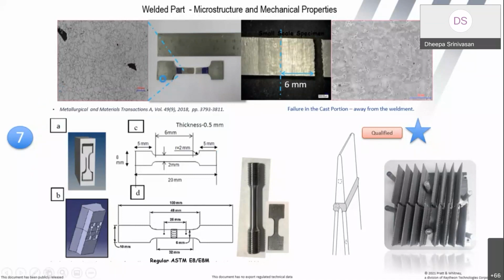But the other challenge I'm highlighting here, apart from small scale testing, is this: what did we do in this particular case? We joined these coupons to the FS641 nozzle. Then we welded it by manual TIG welding. Then we took samples from across the weld. And you can see here the left hand side and the right hand side. So the weaker part is the investment cast FSX414.